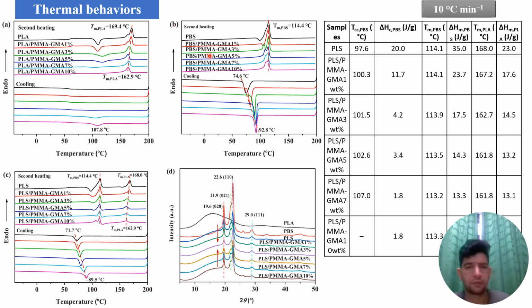Looking at the PBS, PBS has a Tm of 114.4 degrees centigrade. By addition of the compatibilizer, not a big change was observed, but if we observe the second melting peak, it is not a big one, but by adding the compatibilizer the second melting peak is observed, which clearly shows the enhancement of crystallization and also the transition of alpha crystal formation. After that, the Tc of PBS is 74.6 degrees centigrade. By adding the compatibilizer, it increases to 92.8 degrees centigrade. The increase means that it helps in nucleation to improve crystallization.